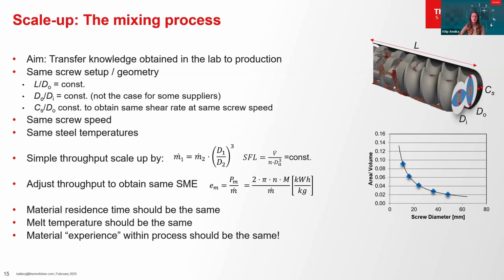A simple law to scale up the throughput is then to keep the specific feed load constant. If that is done, the throughput can further be adjusted to obtain the same specific mechanical energy, which is a measure of the energy input into the material per unit mass. Therefore, you can change the throughput to achieve the same torque.